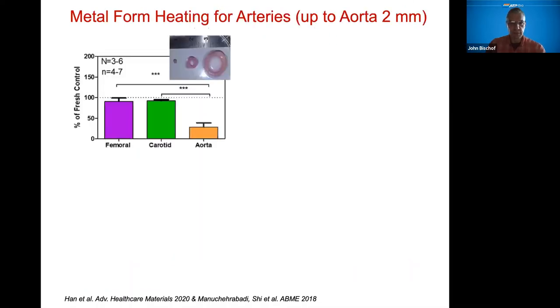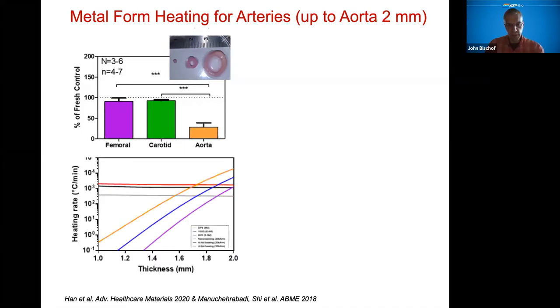So this is just some of the data here. First, femoral and carotid, these are thinner arteries, you know, 1 millimeter or less. And we have been able to, and other people have been able to cryopreserve those. But aorta, you can see very, very low viability because it's so thick. And that's traditional methods. So what we did is we studied this and what we're looking at here, heating rate on the y-axis, thickness of the tissue on the x. And these are different cryoprotective agents.